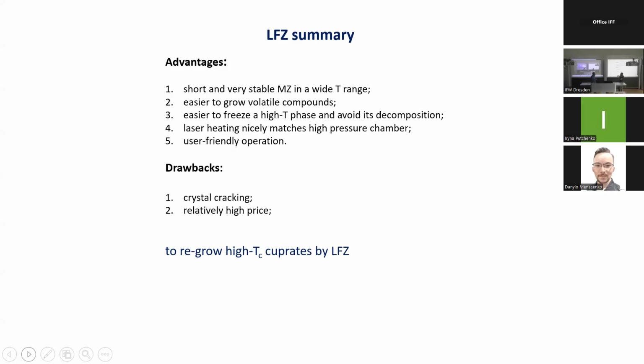Normally we get a molten zone. It's like crystal growth, but we apply a very high cooling rate. So you pass the molten zone at very high speed, much higher than in growth. But in principle, you can do it just to heat, not melt, if it's possible. Sometimes people are doing this approach. They just see when the feed rod shrinks a little bit, and then, okay, now we pass. Sometimes it works for YBCO, for Bisco, yes. Thank you.